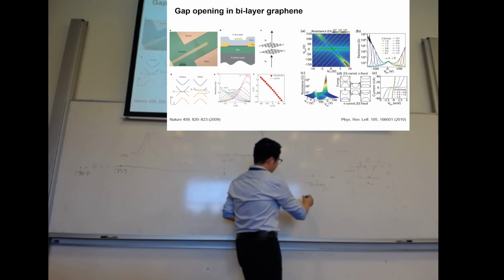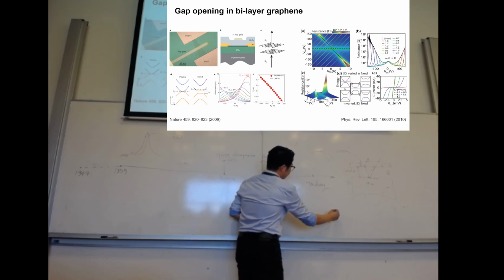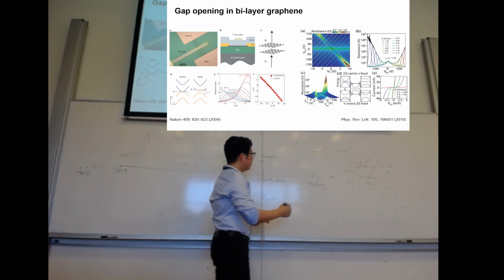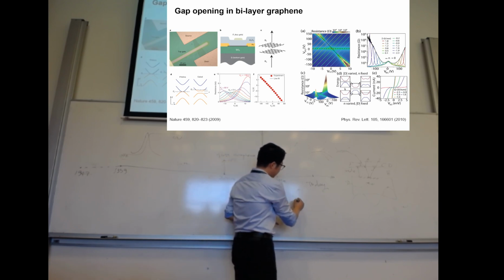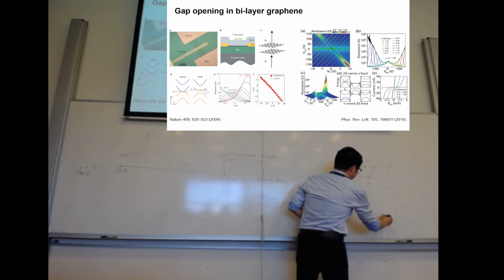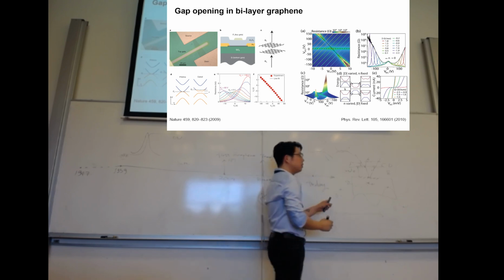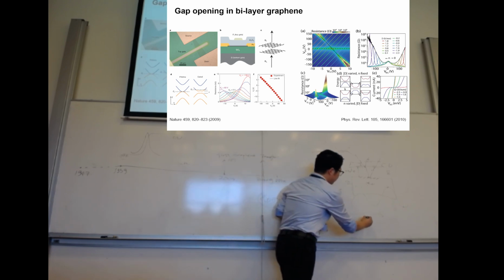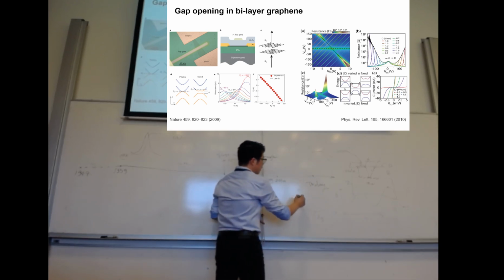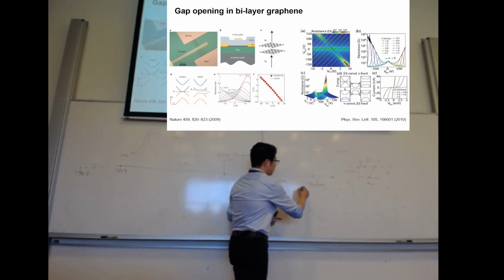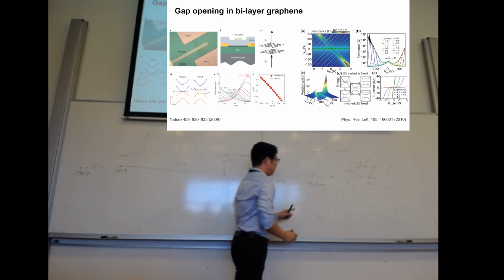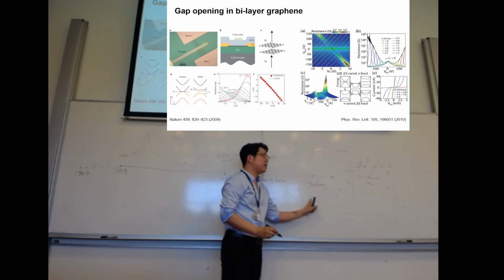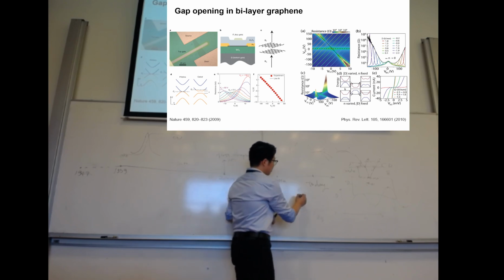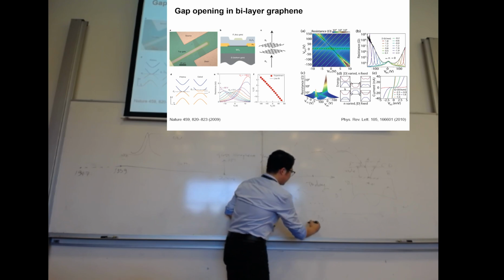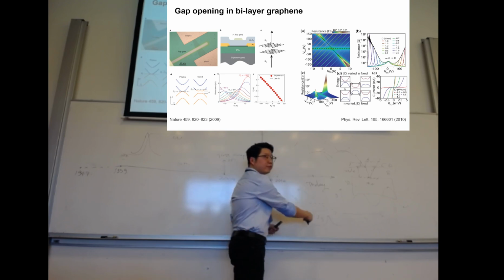So basically, there is a conversion from gate voltage to electrical field, or displacement field, and carrier density. So in this gate voltage space, the resistance peak is lying in this direction. Okay? So if you make a line cut from here, you've got a bottom gate dependence resistance peak.